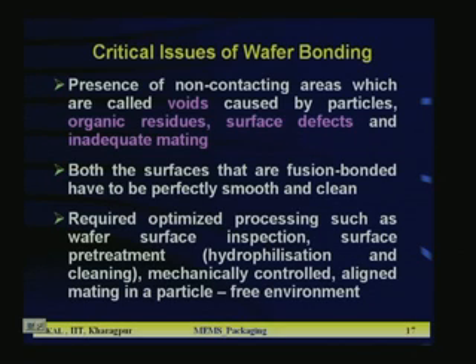So, now the critical issues in wafer bonding, and the critical issues are namely voids. You should go for a technique where the formation of voids is as minimum as possible. And voids are formed from organic residues, surface defects, inadequate mating between the 2 layers, and particle contamination. So, before going for wafer bonding, the surface has to be highly clean, no particles, no organic residue, surface defects as minimum as possible, and it shall be properly mating. Both the surfaces that are fusion bonded have to be perfectly smooth and clean.